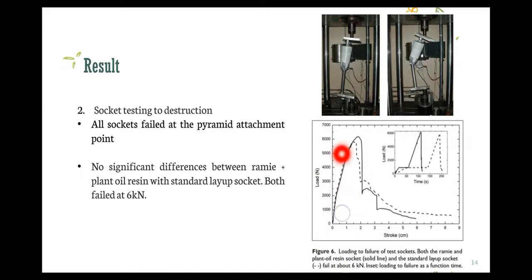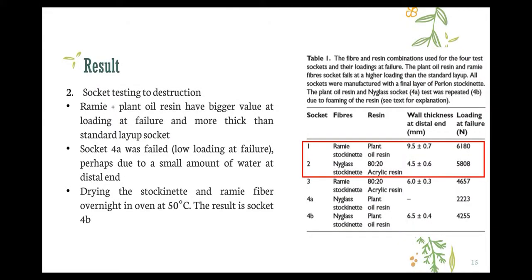This solid one is the ramie fibers with the plant oil resin, and the dotted line one is the standard layup material. And then the ramie and plant oil resin have a bigger value of loading at failure and are thicker than the standard layup socket. The standard layup socket is the nylon glass stockinette, and socket 4A failed because of a small amount of water at the distal end. So to overcome this, they tried again with socket 4B, drying the socket and ramie fiber overnight in an oven at 50 degrees Celsius.